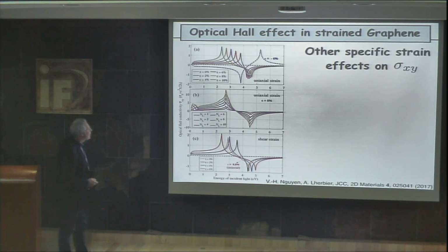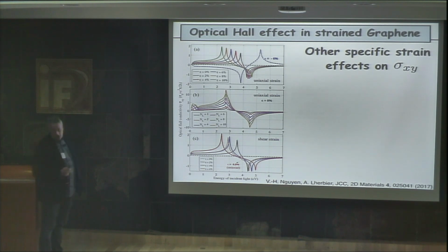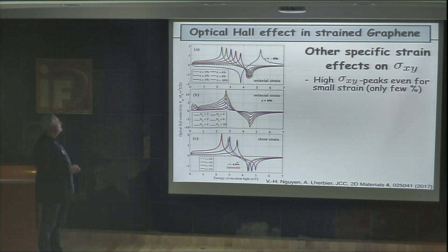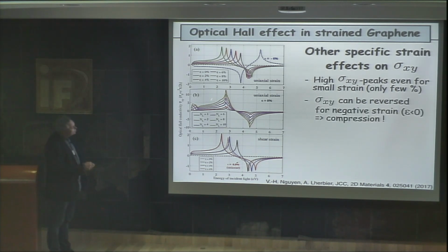Okay. And then we also look at other specific strain effects in sigma xy. For example, we check that for high sigma xy peaks, even for small strain of only a few percent, you see that for only 2% of strain here, you still have this peak. So this phenomenon could normally be observed even for a very small strain in the system. Sigma xy is also important when you have not only a single layer but a few layers, especially if they are randomly oriented, you preserve the Dirac cone, and in that case you should normally observe a stronger effect in the system.